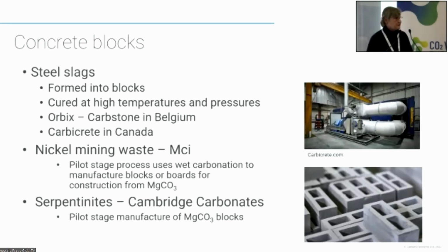Then the whole field of concrete blocks, a lot of companies are using steel slags, again, particularly calcium silicates in steel slags. You can form that into a block, cure it at high temperatures and pressures, and make very nice concrete blocks with no Portland type cement in at all. And Orbix's already mentioned, a spin out from VITO, and there's Carbicrete in Canada as well as a number of other companies looking at the use of steel slags.